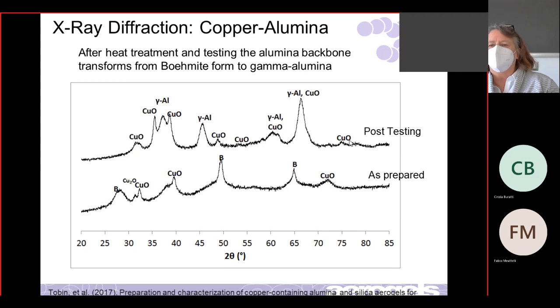So anyways, what this tells us, it's hard to do X-ray diffraction because we have very little amount of the metal in there. The aerogel itself is amorphous. Much of it is amorphous, so you can't see, especially the silica. But we are able to pick up some of these peaks. It's hard to do, but you can get them.